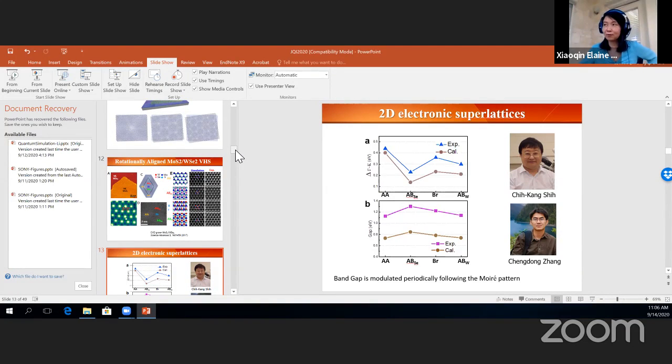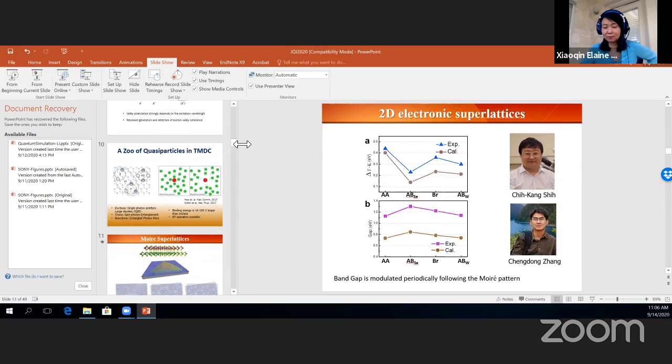Where are the electron and hole, right? So they're in the material that's most heavily studied because of its particular band structure, WSe2. So people have seen trions, both intralayer trion and interlayer trion. What that means is, for intralayer trion, the electron-hole pair and the excess electron are in the same valley. And for interlayer, the excess electron is in the opposite valley. And it turns out, if my memory serves me right, the interlayer exciton is yet again a few meV lower than the intralayer exciton.